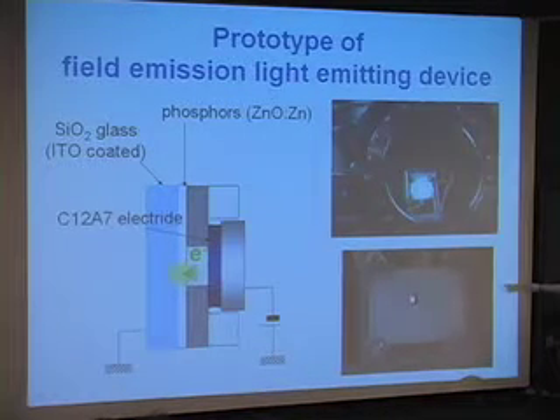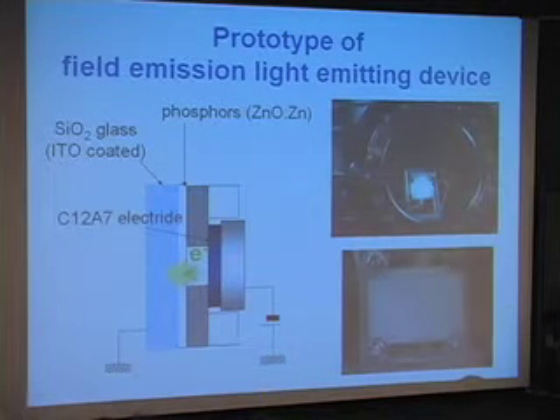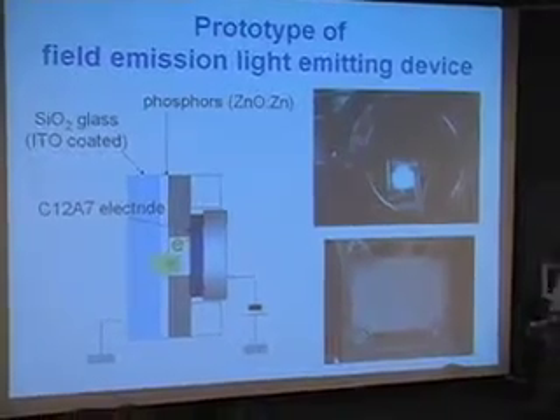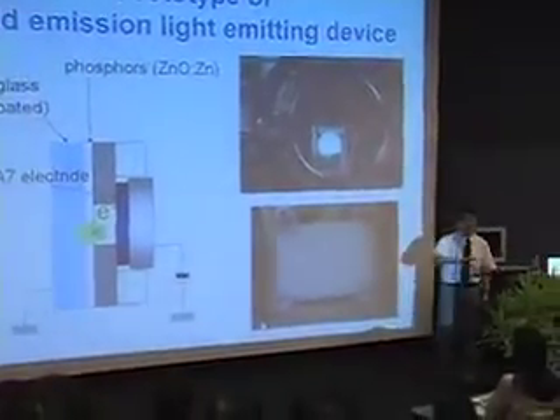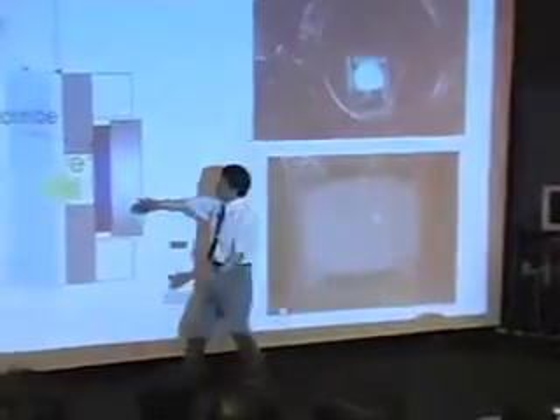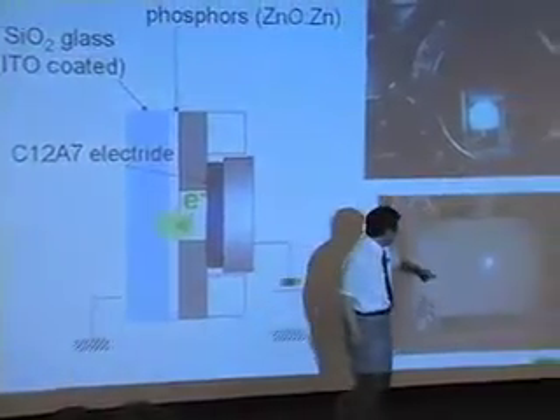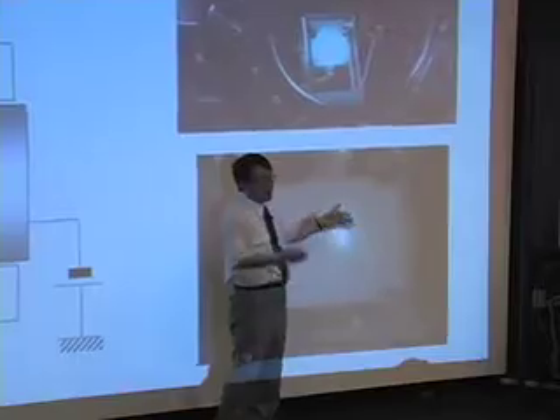This is a demonstration of electron emission from the sample. The sample is mechanically polished, and we apply a voltage, and it hits the phosphor pasted on the opposite side of the electrode. What happens? Electron comes out just by applying a DC voltage.